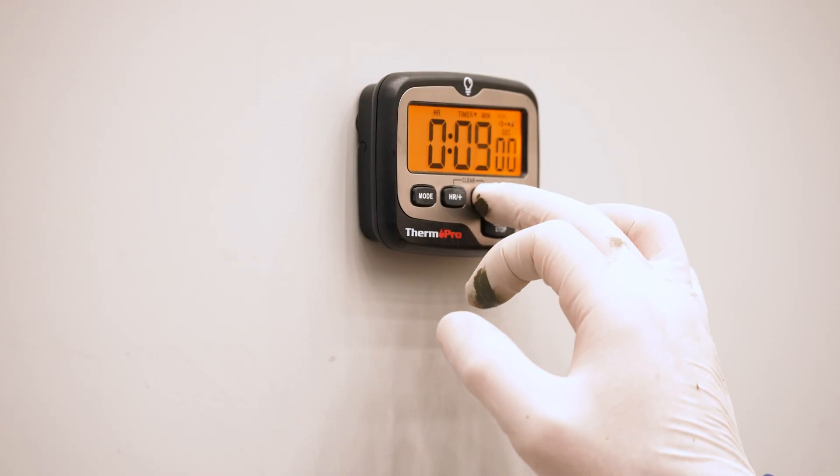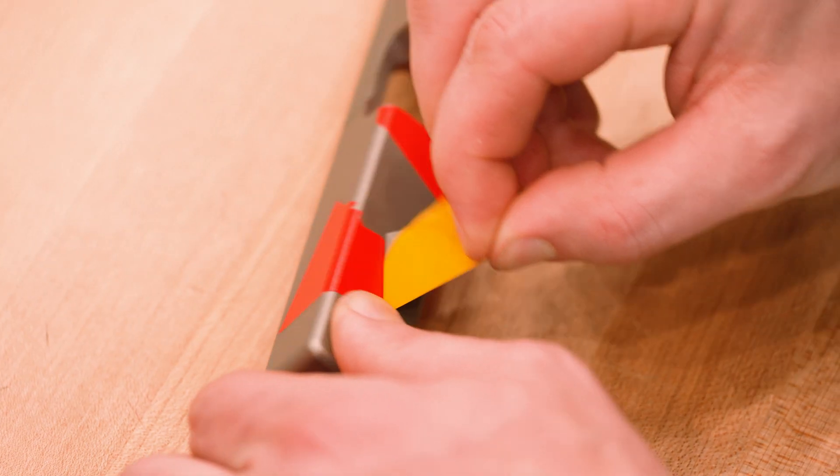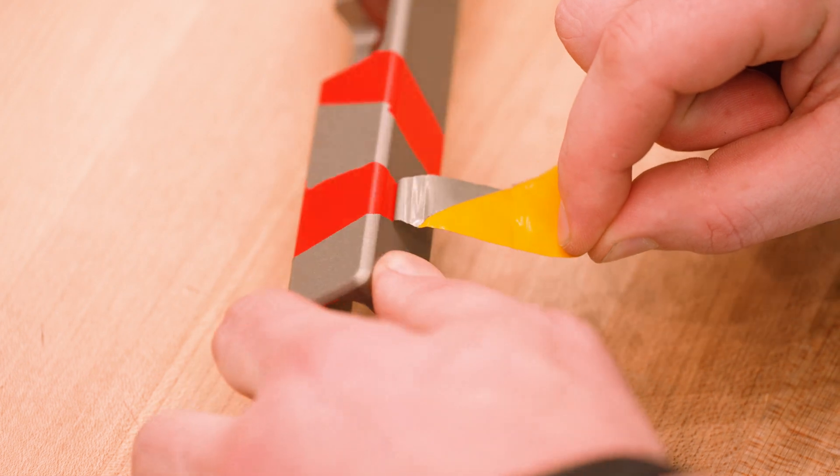However, you must be careful not to leave an item in for too long, or you may cure the coating to a point that the layers become chemically resistant to each other. If this happens, the top coat will be rejected and not adhere properly.